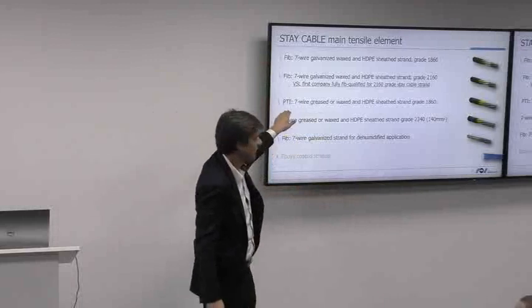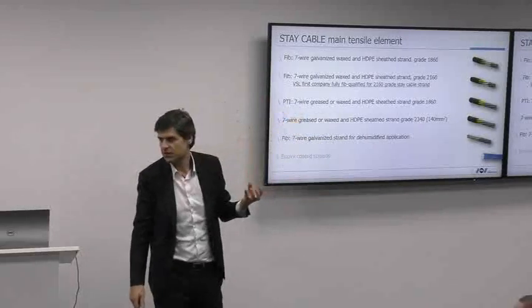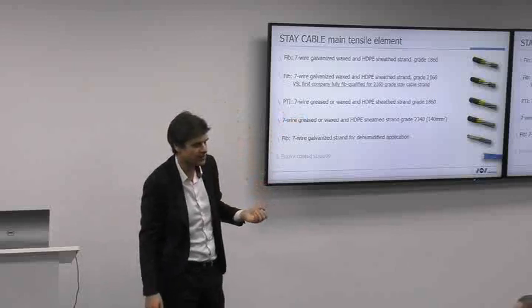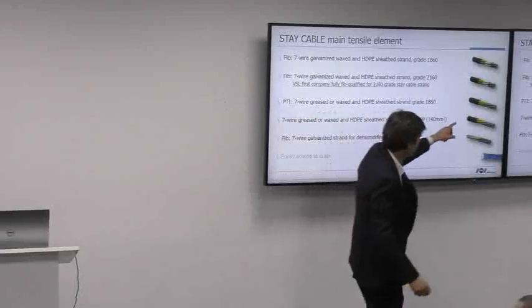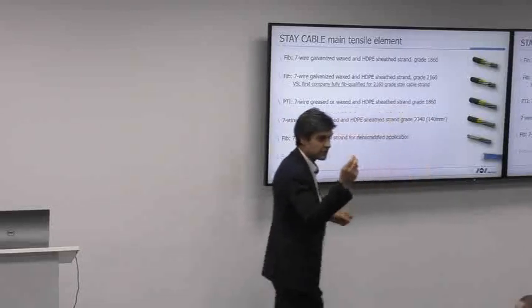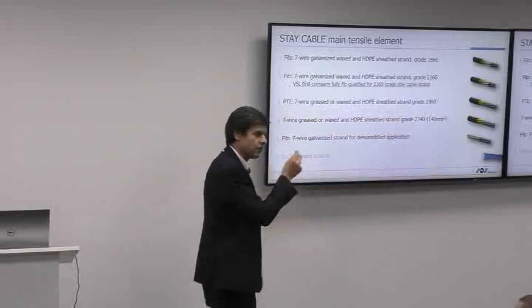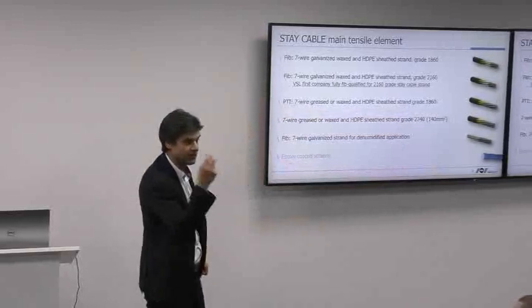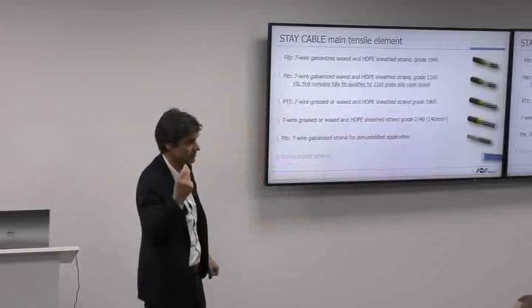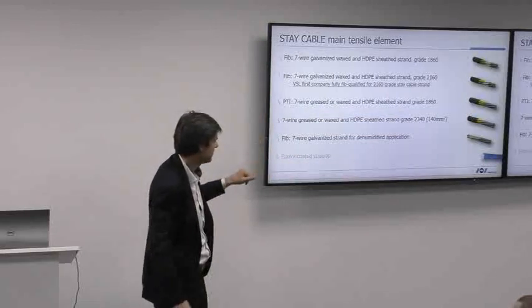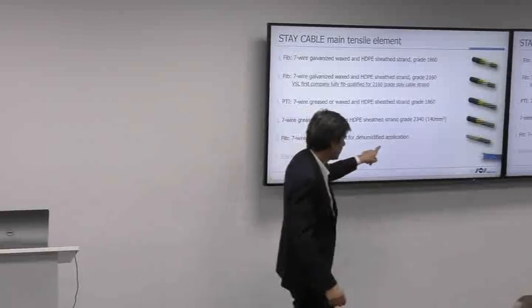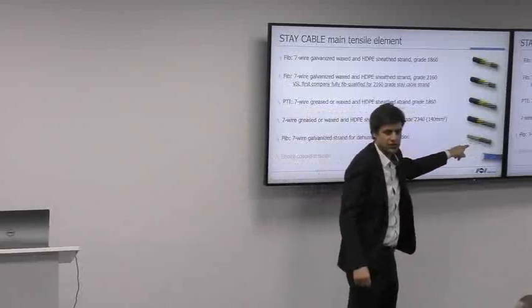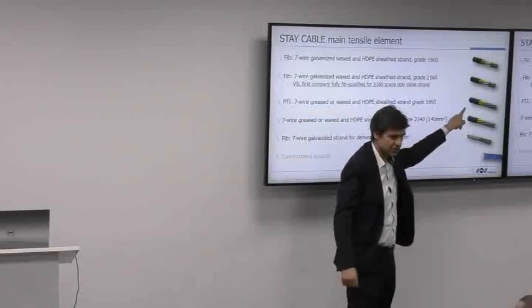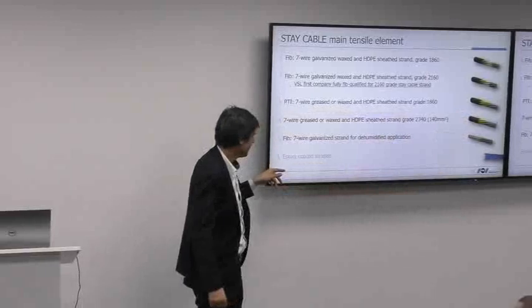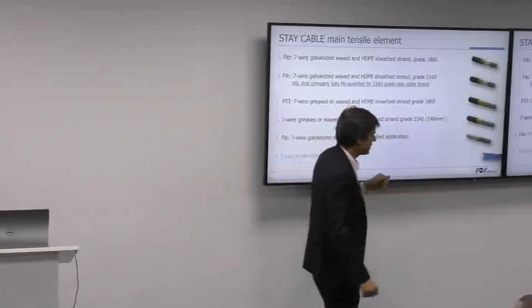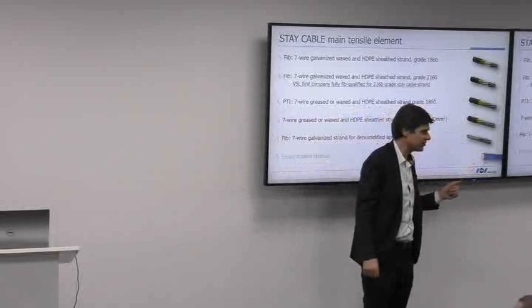So this is a strand, we call it PTI strand, which is the strand as it is recommended in the US, which has no zinc, and therefore has slightly better behavior sometimes, and slightly lower for other aspects. Talking about fretting, for example, is a bit less. Talking about ductility is a bit better due to the no zinc on the strand. VSL is making use for a specific concept, I'll show later, strand without any sheathing and injection. And eventually, we're talking about epoxy-coated strand. VSL has reference experience with this type of strand, but VSL do not recommend the use of that strand.